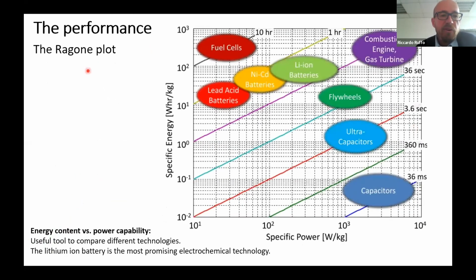So based on the performances in terms of specific energy and specific power, batteries can be classified against themselves, but also against other devices in terms of the Ragone plot, which is a log-log plot where we put the specific energy versus the specific power. And you can see that lithium-ion batteries are the best performing battery system right now, and we're still increasing that. And this is getting competitive with other technologies.